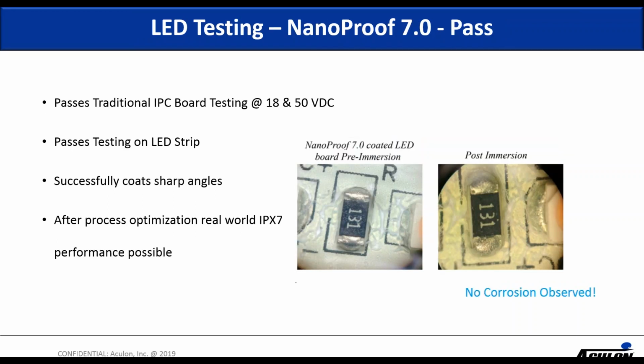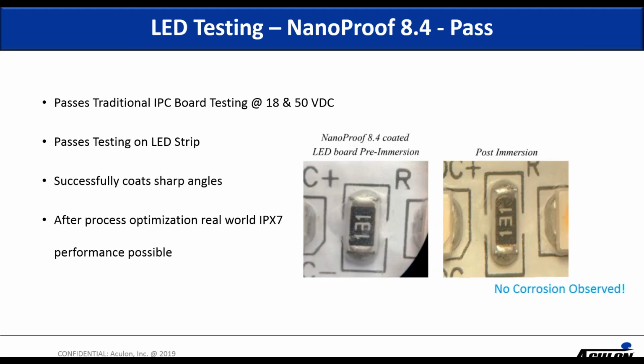And now, to compare to the NANOPROOF-7 series, which passed the IPC board testing at both 18 and 50 volts, it also passes the LED strip. So the NANOPROOF line of materials is designed to actually coat the edges of the part so that you get not only good performance on the IPC test boards, but also in real-world scenarios when you have three-dimensional components which need protection. Again, a repeat of this with the 8.4.